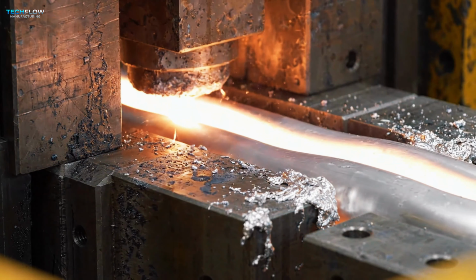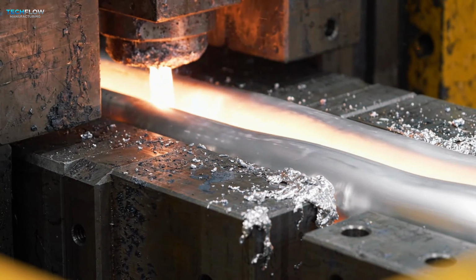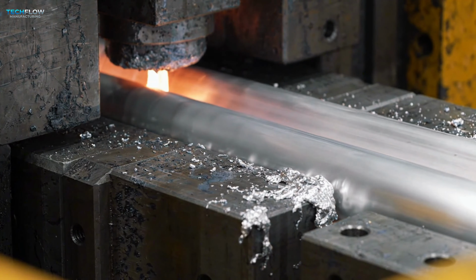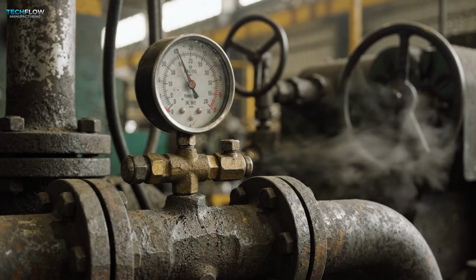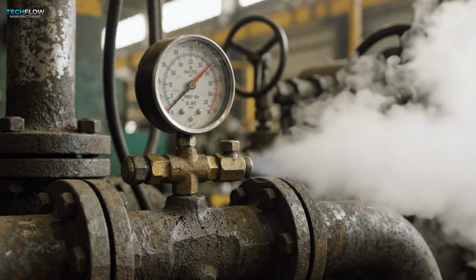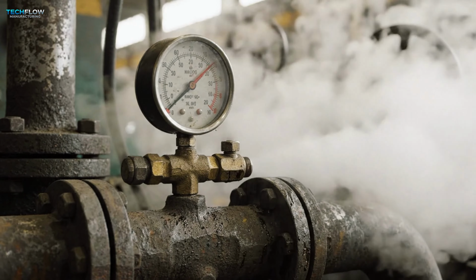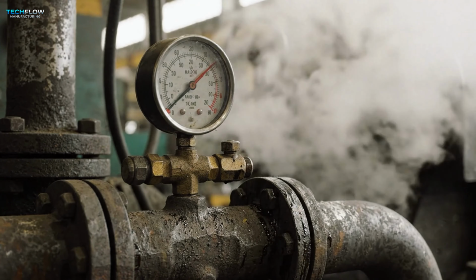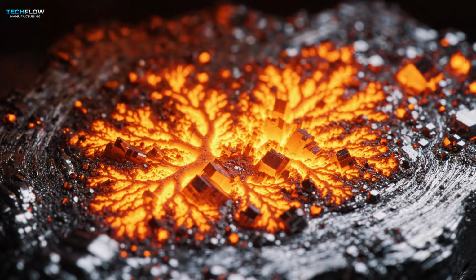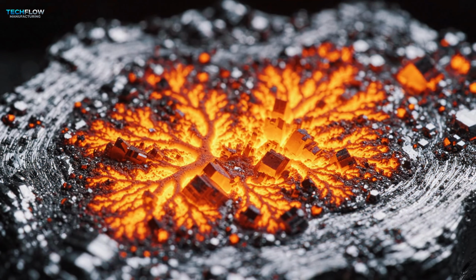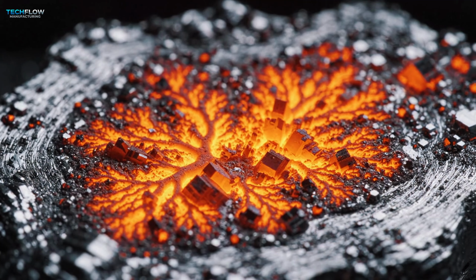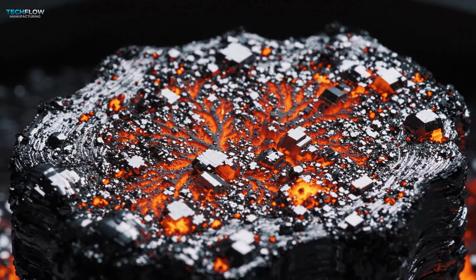It is engineered to ensure a laminar flow, preventing turbulence and oxide formation. Once the cavity is full, a secondary intensification pressure is applied, squeezing the cooling metal to ensure perfect density. This is the mushy zone phase, where the alloy is neither fully liquid nor fully solid, a critical moment for structural integrity.